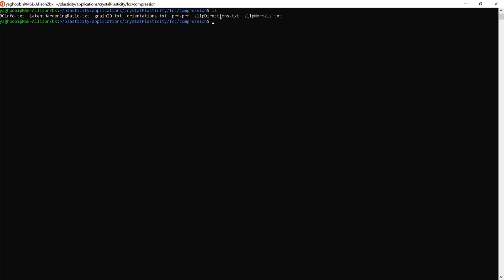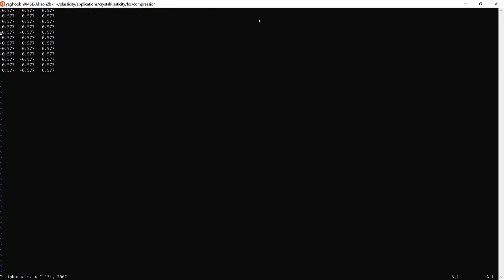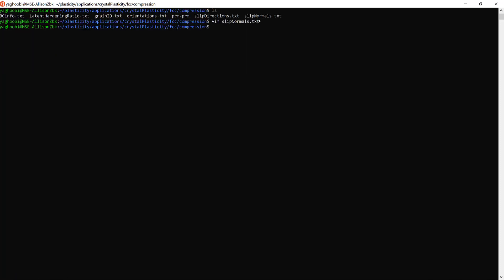As you can tell from the names, slip_directions and slip_normals include the crystallographic information of slip systems in the Cartesian coordinate system. Each of these files should have a number of rows equal to the number of slip systems. For example, in an FCC system we have 12 slip systems, and if you open one of these files you can see there are 12 rows.